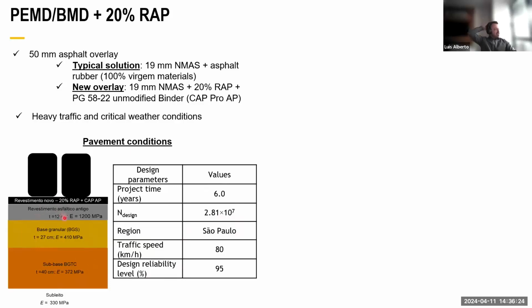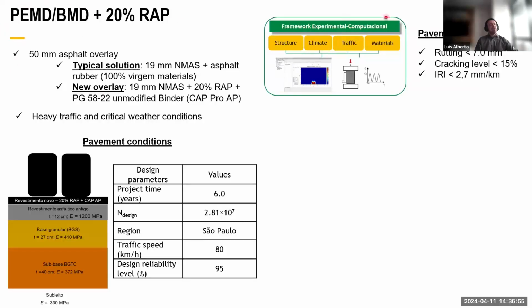The good news from the pavement structure is that it looks like we don't have fatigue life dominating the process here. The main concern is rutting, because we are using asphalt rubber, a material that has very nice rutting performance in Brazil, and we are replacing it with a 58-22. So in order to apply this material on this road, we ran our performance engineered mix design. We have some road concession pavement design limits. For rutting, the maximum is 7 millimeters, cracking the maximum is 15%, the IRI is 2.7. We have a very high level of IRI allowed on our roads in Brazil.